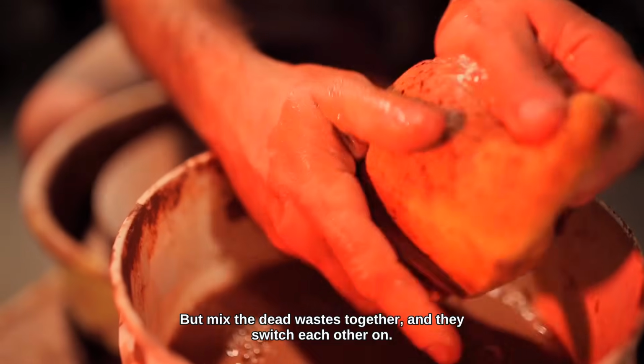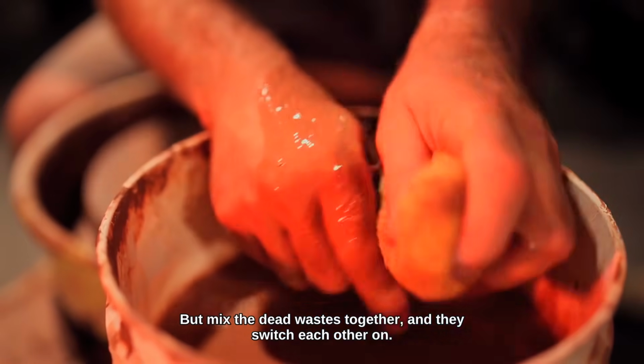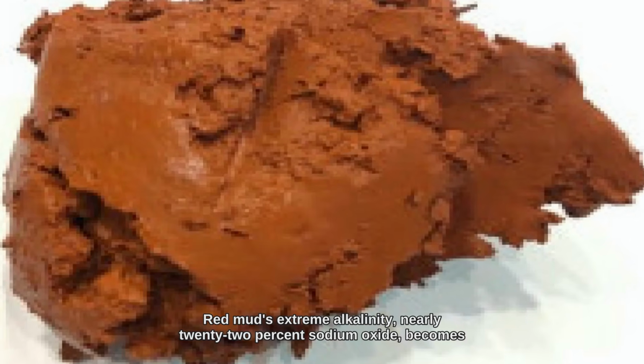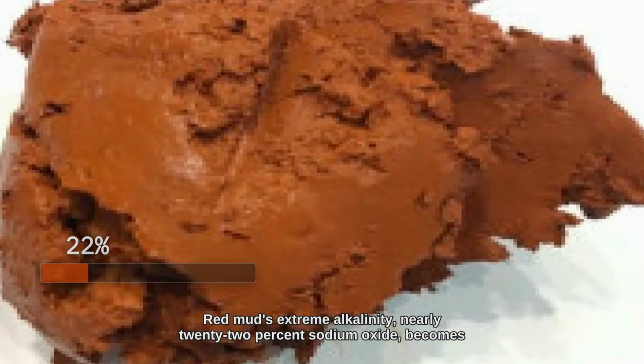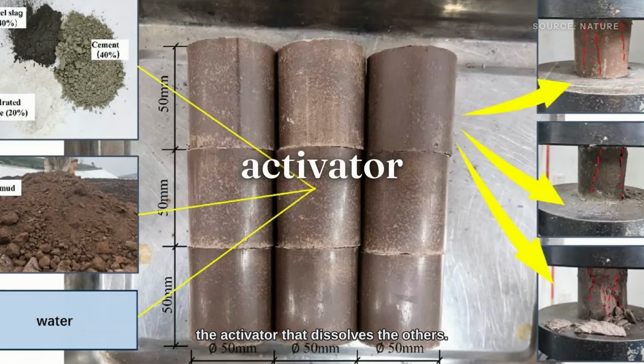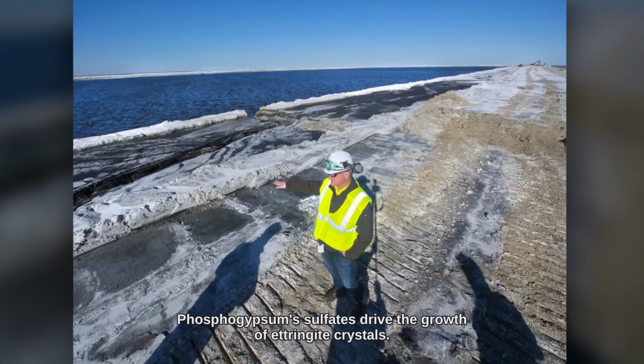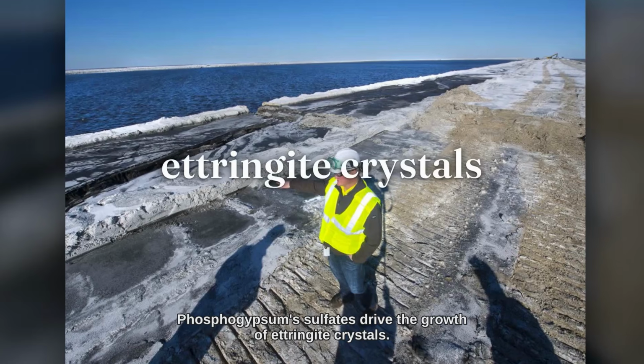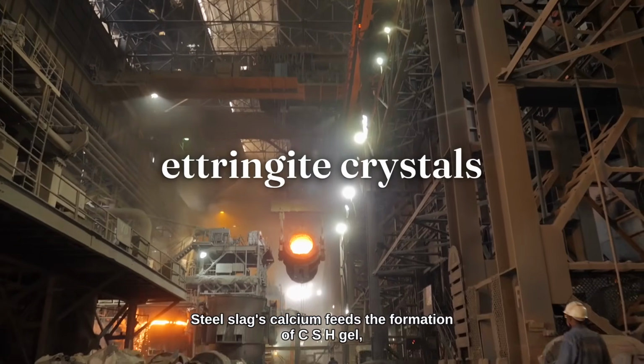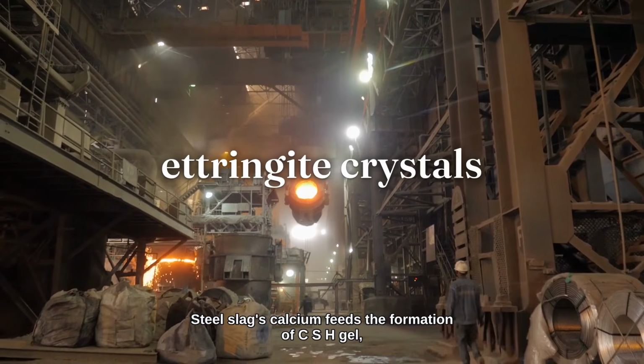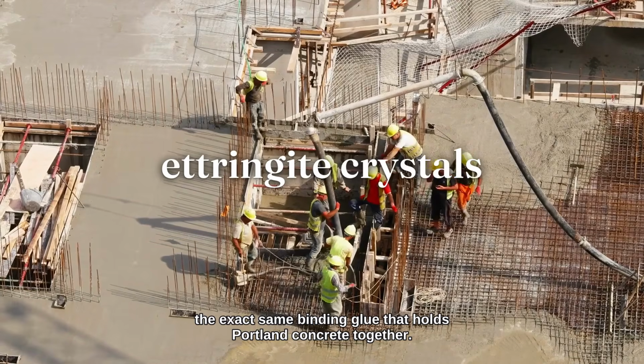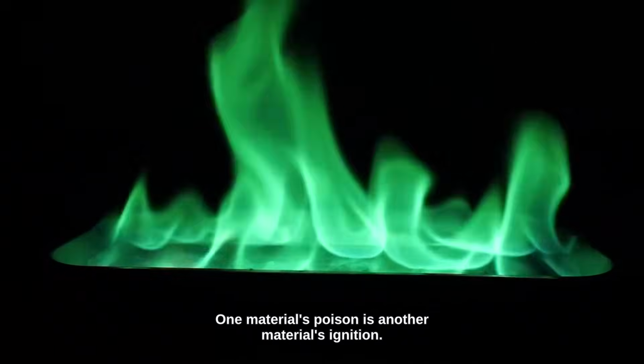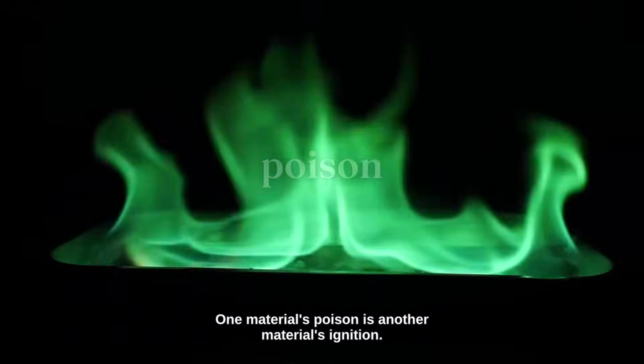But mix the dead wastes together, and they switch each other on. Red mud's extreme alkalinity, nearly 22% sodium oxide, becomes the activator that dissolves the others. Phosphogypsum sulfates drive the growth of ettringite crystals. Steel slag's calcium feeds the formation of CSH gel, the exact same binding glue that holds Portland concrete together. One material's poison is another material's ignition.